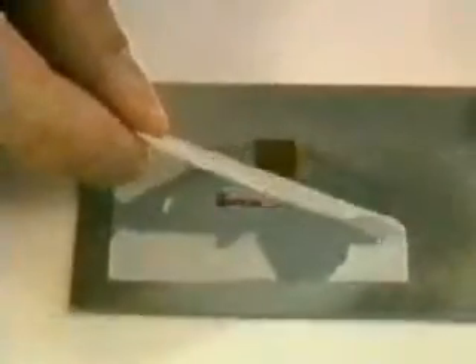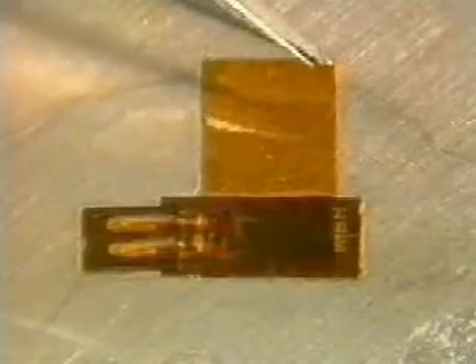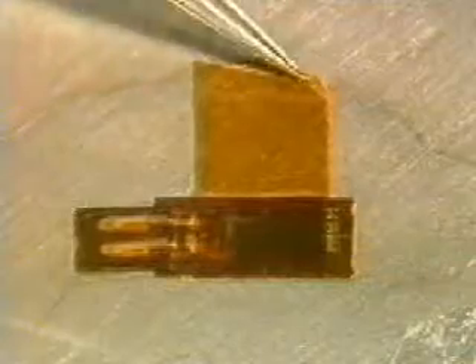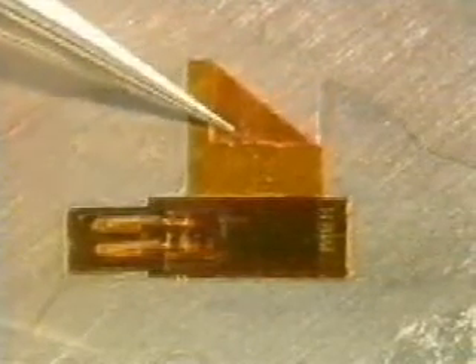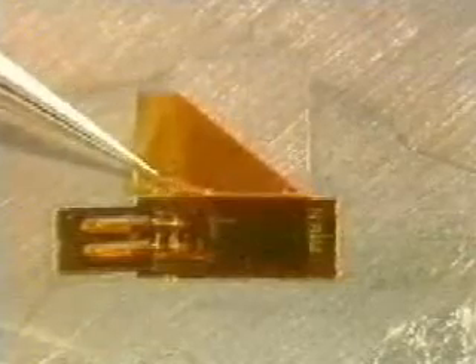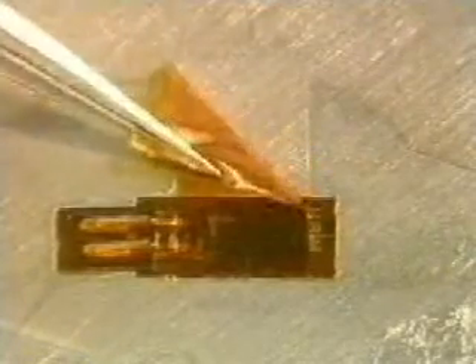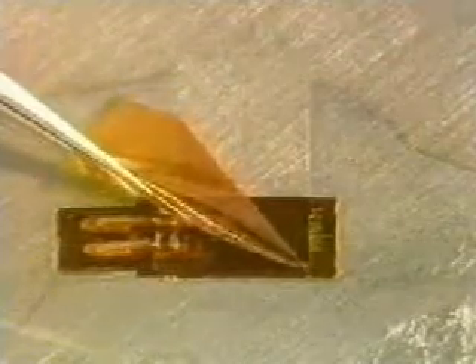After the Teflon film is removed, you will be able to see a matte zone where the adhesive has bonded firmly. At points where the thumb pressure has not had an effect, the adhesive is still fluid and the surface shines. The Teflon film and brief thumb pressure are sufficient to cure the remainder of the fluid adhesive. The adhesive strips can now be removed. The cement achieves its full strength only after half an hour, and it must not yet be subjected to high loads. Therefore, peel off the adhesive strips flat and carefully in the direction of the connections.